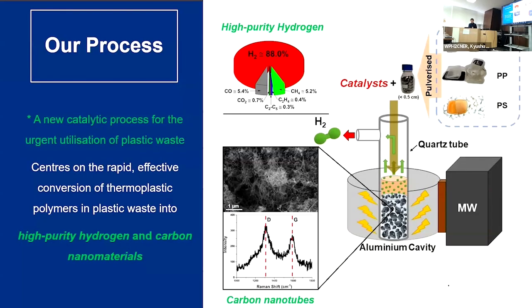So this summarizes how amazingly simple it is. We are not doing some very complex step-by-step reaction, but that is the beauty of microwave catalysis. Once you find a good candidate, a good catalyst to work on, what you need to do is just mix your catalyst with your pulverized or ground or shredded plastic pieces and put it into the microwave. Just give it a go. And after 20-30 seconds, you will get your clean hydrogen and the carbon nanotubes on site.